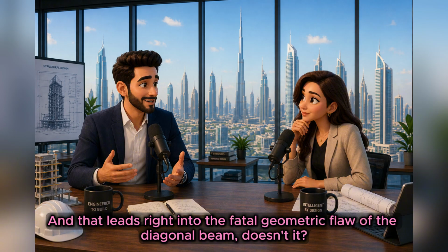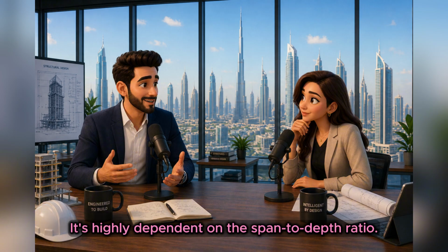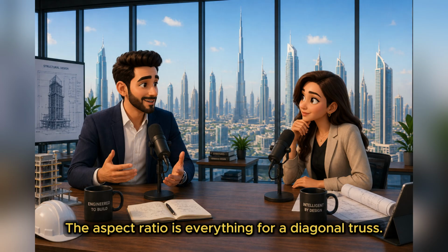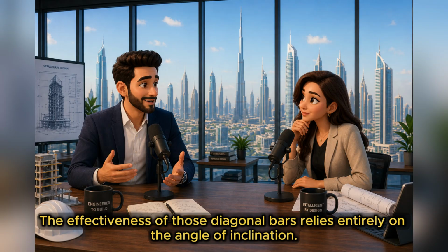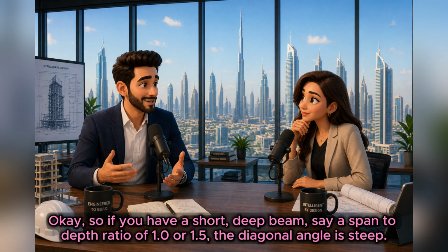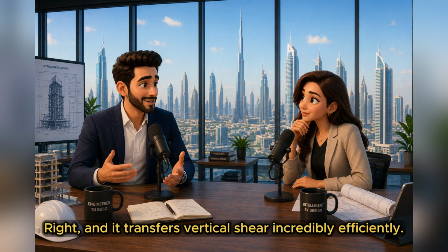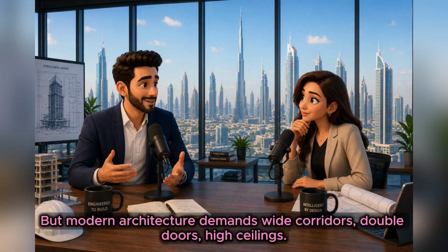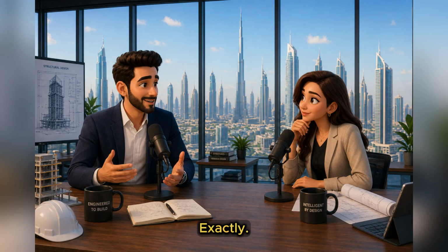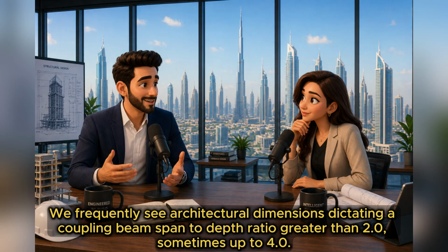And that leads right into the fatal geometric flaw of the diagonal beam, doesn't it? It's highly dependent on the span-to-depth ratio. The aspect ratio is everything for a diagonal truss. The effectiveness of those diagonal bars relies entirely on the angle of inclination. Okay, so if you have a short, deep beam, say a span-to-depth ratio of 1.0 or 1.5, the diagonal angle is steep. Right, and it transfers vertical shear incredibly efficiently. But modern architecture demands wide corridors, double doors, high ceilings. Exactly. We frequently see architectural dimensions dictating a coupling beam span-to-depth ratio greater than 2.0, sometimes up to 4.0.